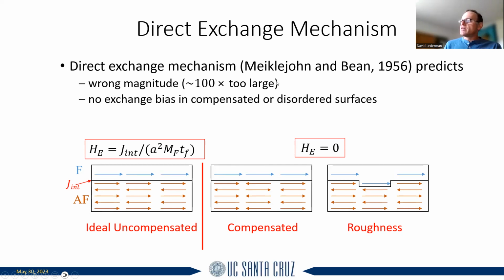So the first one is that this gives you the wrong magnitude. If you just put in reasonable numbers, you would get a number that's maybe 100 times too large compared to the effect that's actually observed. And the other important fact is about a compensated surface. Imagine that instead of an antiferromagnet with one sublattice to the right, one sublattice to the left, alternating like that, you have both sublattices present at the surface. This is called a compensated surface, because now you have both sublattices. There should be no net exchange, because this one would have exactly the opposite exchange from this one, and the whole effect should cancel. Maybe you would have a wider coercivity, but this should cancel.